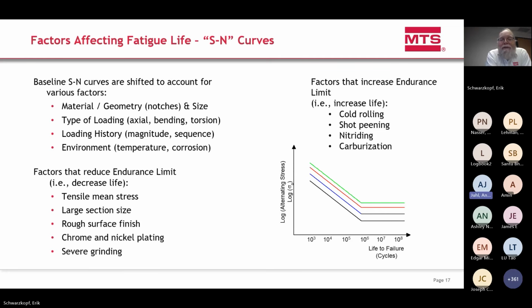Things that increase the life include surface compression treatments, like cold rolling, shot peening, nitriding, or carburizing. If you put a compressive layer on the surface, the crack doesn't open nearly as quickly.